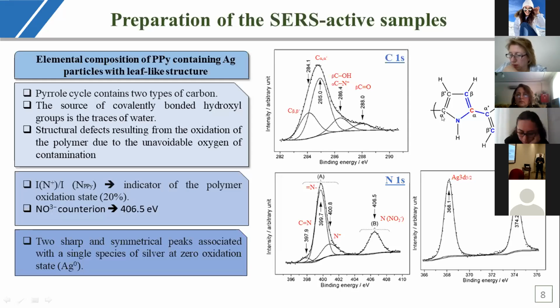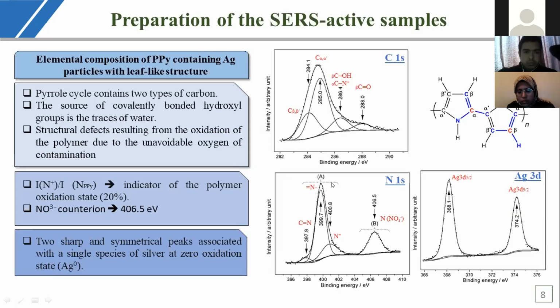The XPS spectrum of nitrogen contains 2 regions. The first is the nitrogen atom of the pyrrole: the main band at 399 electron volt is associated with neutral nitrogen, the one at 400 electron volt with positively charged nitrogen, and the peak at 397 is assigned to a C=N structural defect.